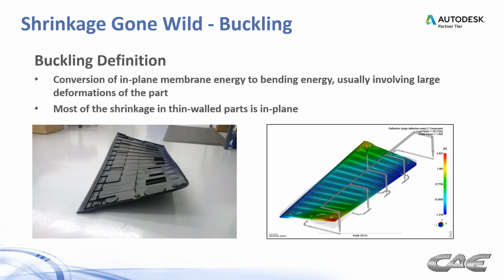Okay, and this is one of these areas in mold flow that is not very well understood, I guess. I shouldn't say well understood, but not often used. It's well understood, but it's not often used. Standard mold flow, if you're not paying attention to buckling, you can get some very wrong answers in terms of the predictions for your molded part. So buckling is really important to pay attention to, especially when you're going thinner and thinner. And you can see this on this particular part, mold flow picked it up very well.